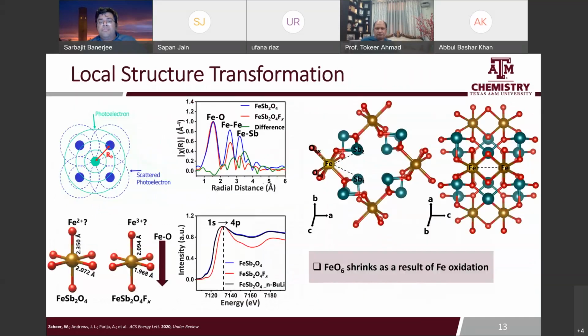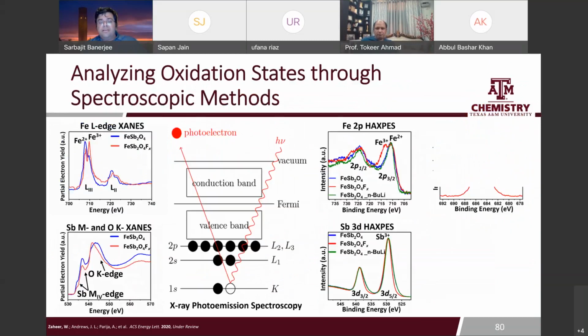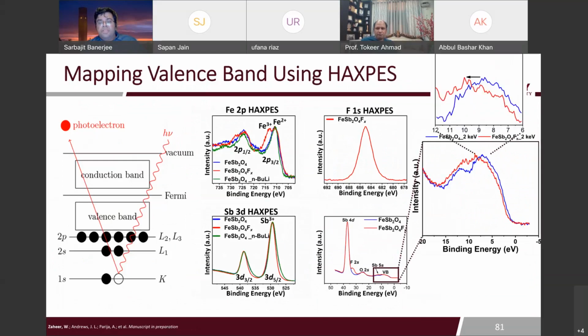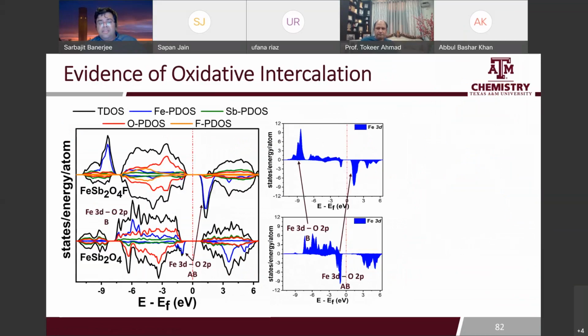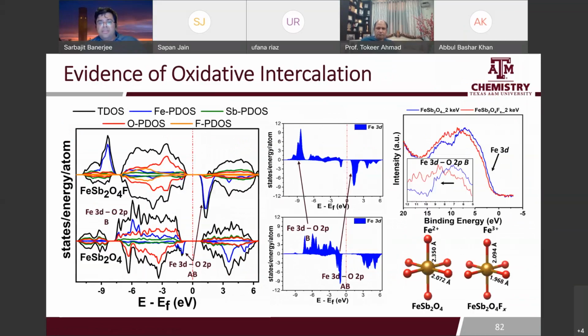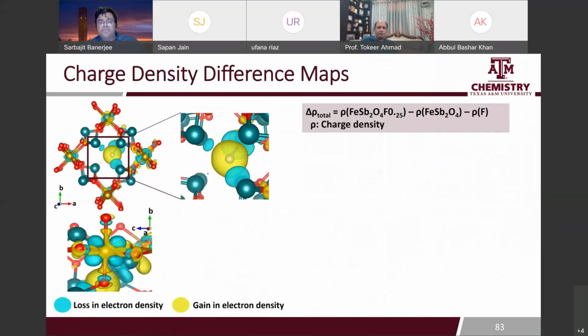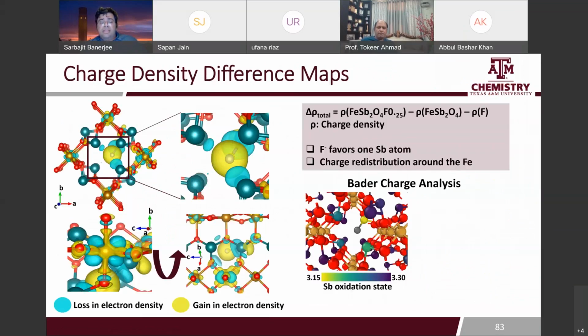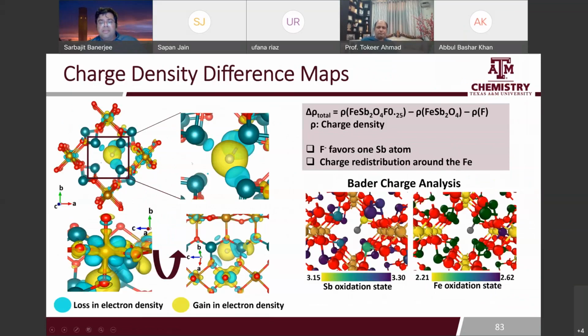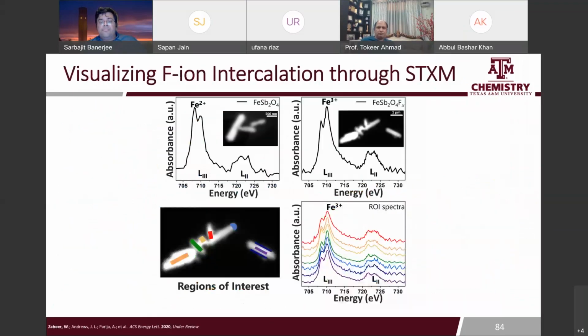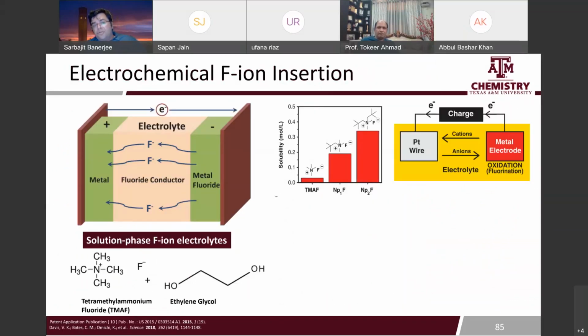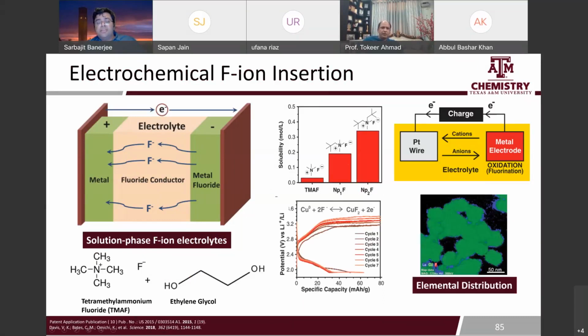You can see this oxidation reaction happen, and the iron octahedron shrinks, the antimony oxide tetrahedron expands. I'm going to skip through some of the details of what exactly happens here. We're writing a paper about this, and it's essentially about how the antimony lone pair helps in this reaction. But you can see here the charge density difference maps, which show that the iron is oxidized, and the antimony actually is not completely an innocent spectator. The lone pair of antimony helps in the movement of fluoride ions. So moving towards electrochemical fluoride ion insertion will require coming up with new electrolytes. There's a lot of work in this area, coming up with room temperature fluoride electrolytes, which is going to be critical to do electrochemical fluoridation across these chemistries.